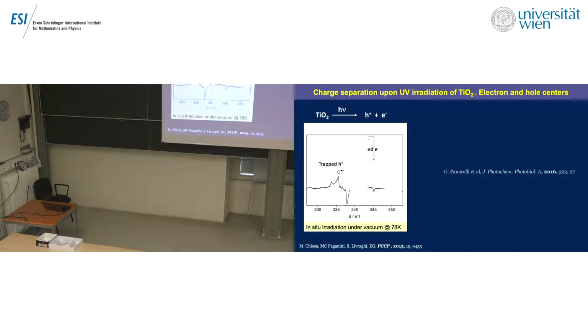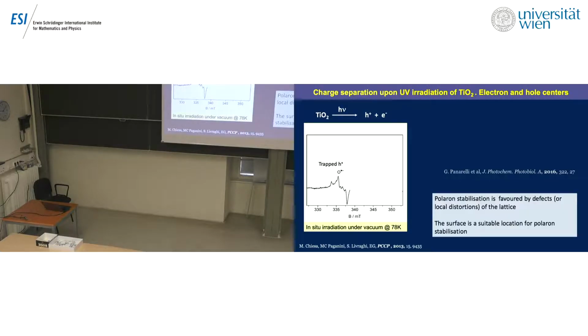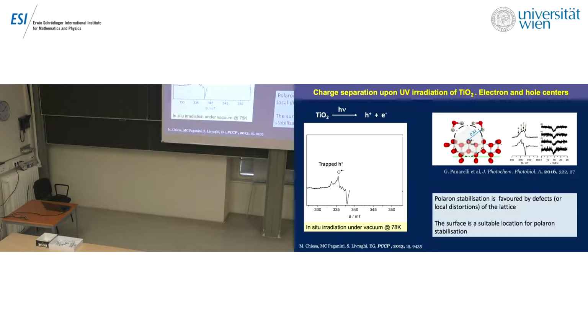So, what can we do about the hole polaron in TiO2? It has been said something yesterday by Cristiana Di Valentin. We have really seen that the polaron stabilization is favored by defects. Everybody in this audience knows that. But one of the possible defects is the surface of the system. In particular, if the surface is hydrated, we have measured with a technique called ENDOR, or electron-nuclear double resonance, the interaction of the unpaired electron here on oxygen with the water, the physisorbed water that stays around this site, with some nest of this type, okay? We can just say something about the distances between the unpaired electron and the proton of the water, and it is 0.32 nanometers, and so this is compatible with a physisorbed layer.